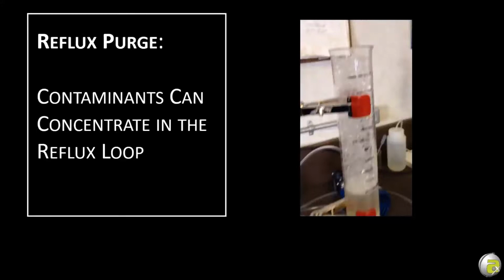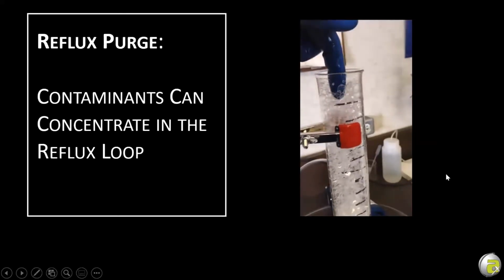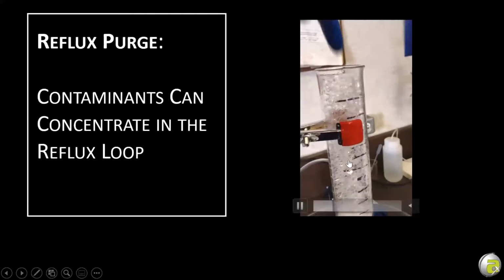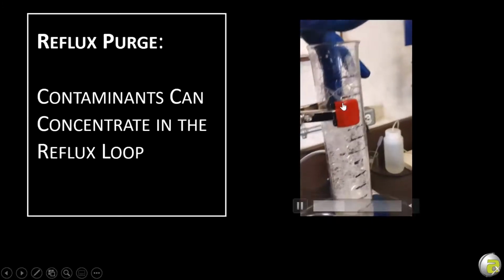And I mentioned earlier reflux purge. The reflux is a great repository for contaminants. A lot of contaminants in your amine process are volatile enough that they might go overhead and then are recondensed. So they tend to concentrate in that reflux loop. And whenever you've got a foam that forms geometric shapes like here, pentagrams, hexagrams, as long as they're circles, they're not bad. But once you've got a geometric shape, that's a stable foam.